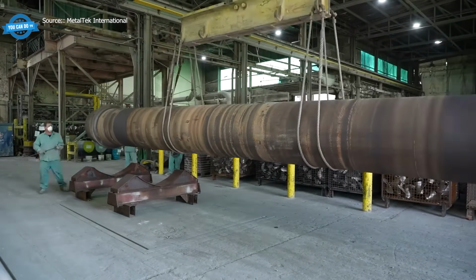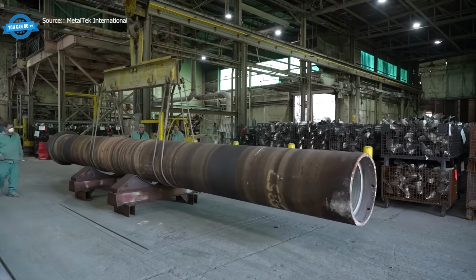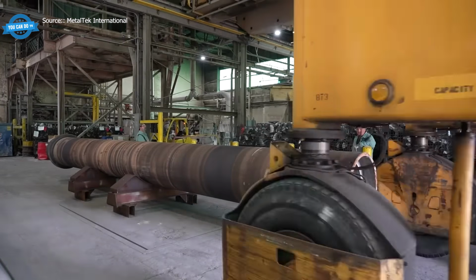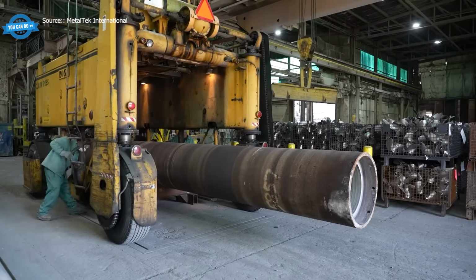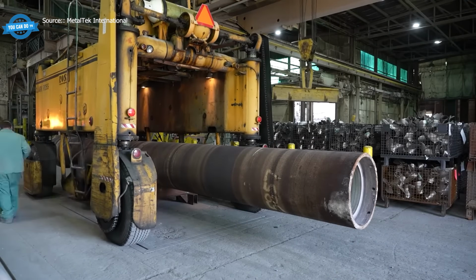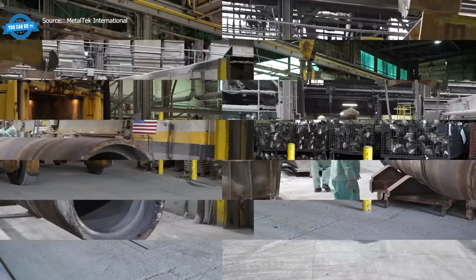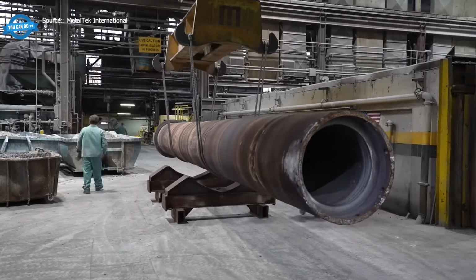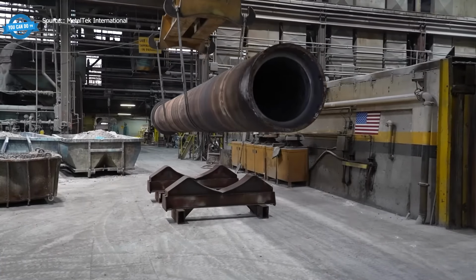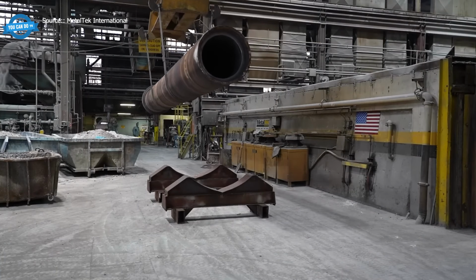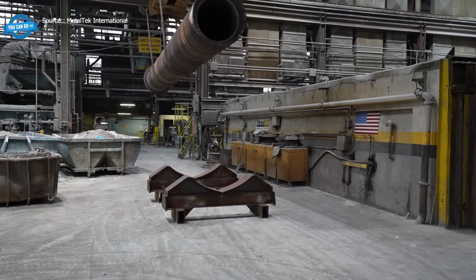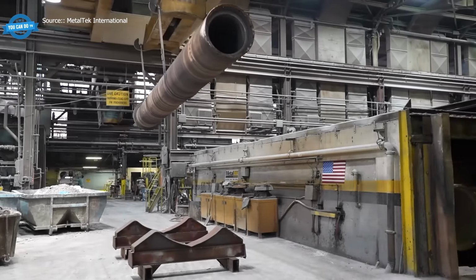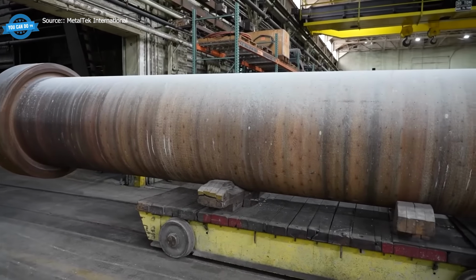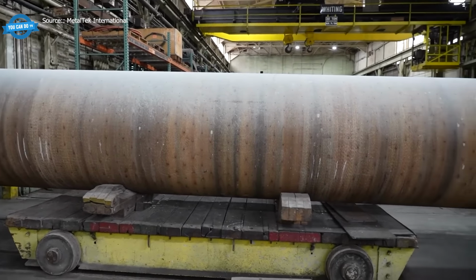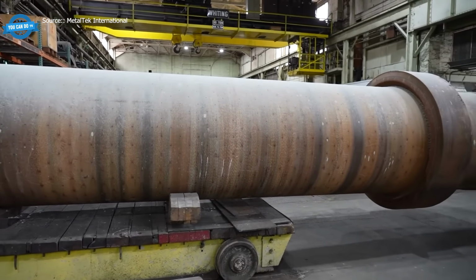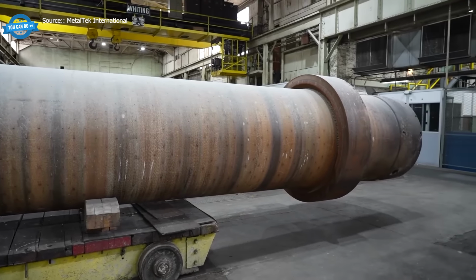Imagine a mold big enough to cast a pipe you could walk through. Now imagine spinning it fast enough to fling molten metal outward against its walls without the whole assembly tearing itself apart. Centrifugal castings at this scale serve defense, paper mills, and heavy process industries where seamless tubular geometry with dense grain structure is not optional. Success depends on three things: stable mold rotation, controlled temperature, and a carefully regulated pouring rate.